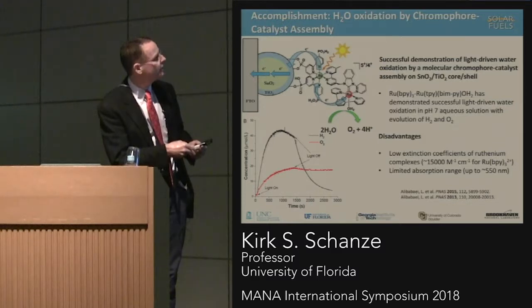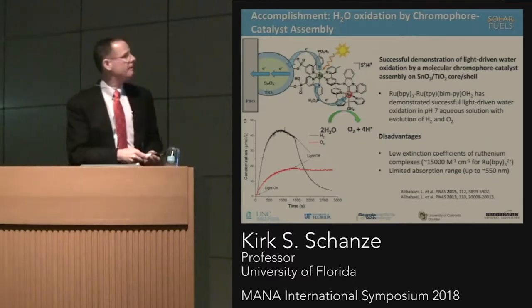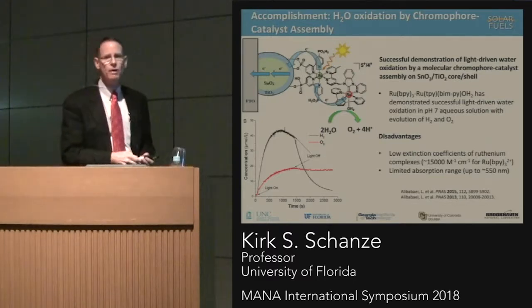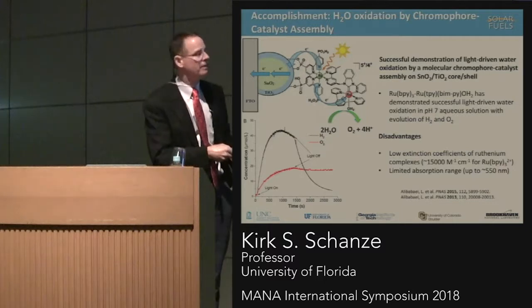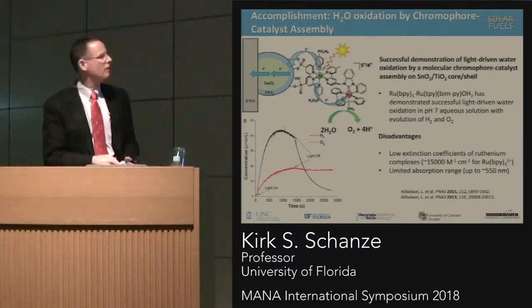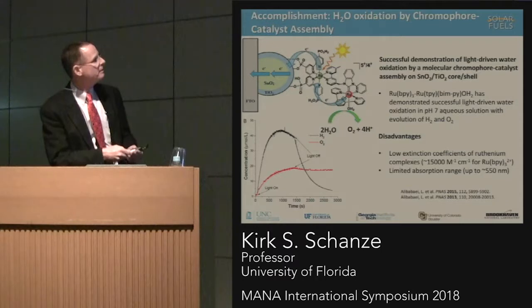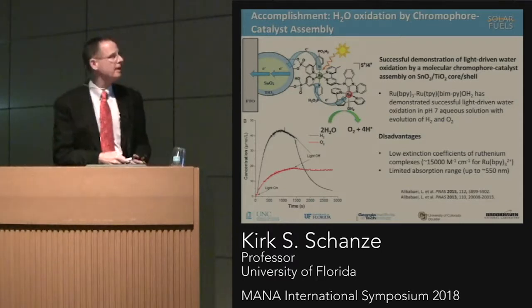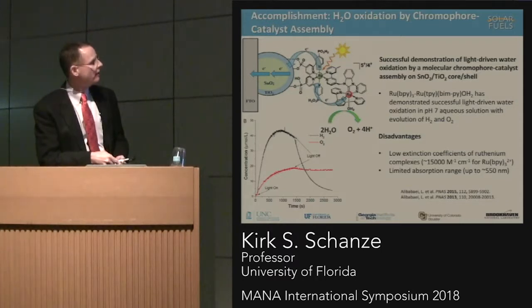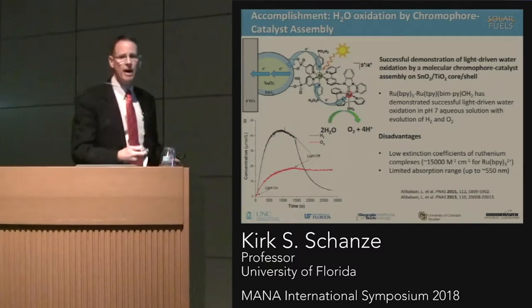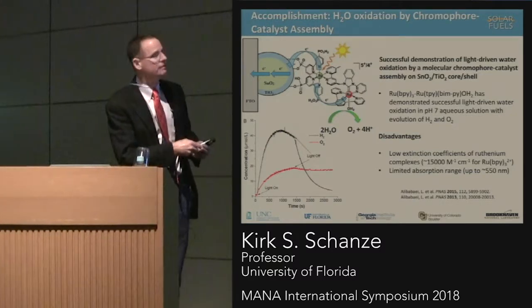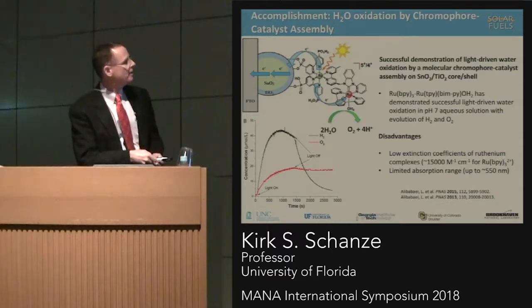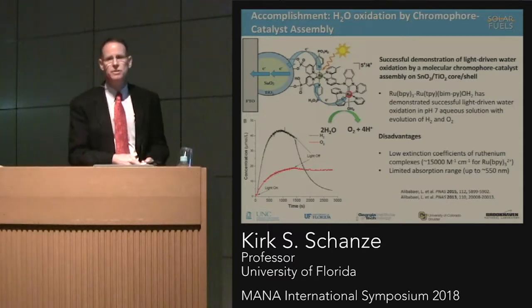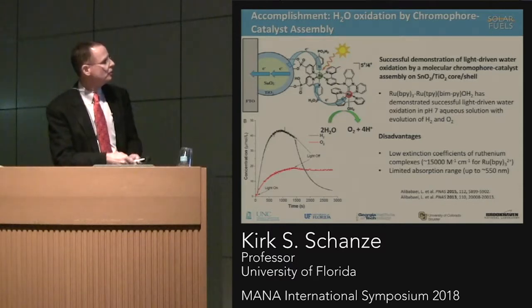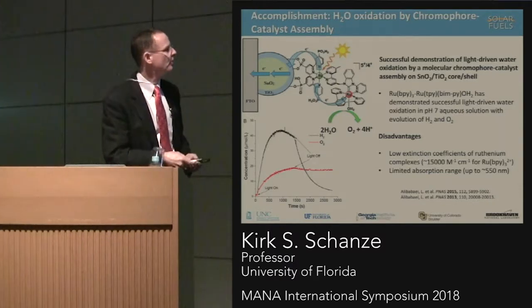That ruthenium is linked to a second ruthenium center, and if you look at this, this is an organometallic ruthenium that has a carbene ligand and some pyridines and then an aqua ligand. This ruthenium complex is a competent water oxidation catalyst. So when it's oxidized up to a high valent state, it can turn over water oxidation. So this assembly, when it's at a metal oxide interface and is illuminated, generates dioxygen by water oxidation, and then the electrons that are injected into the electrode can be collected at a platinum counter electrode and generate hydrogen. So these are two real-time plots showing the oxygen and hydrogen production.